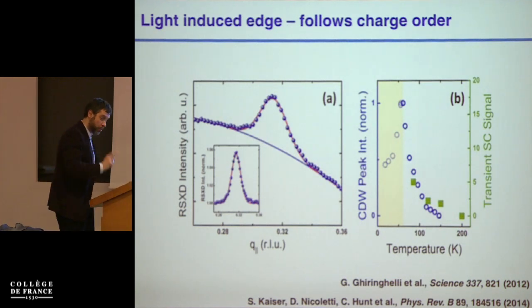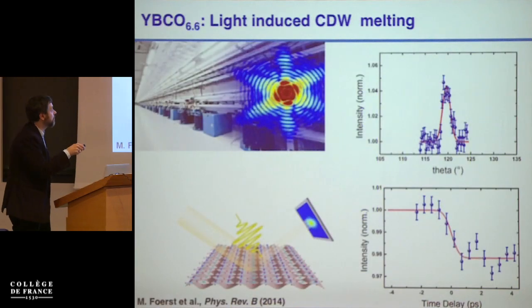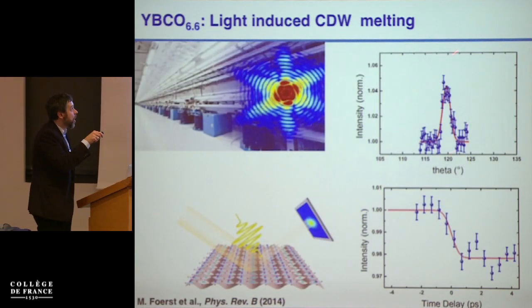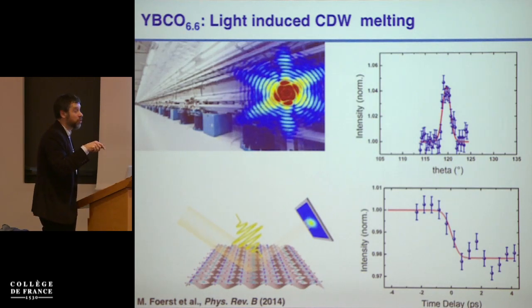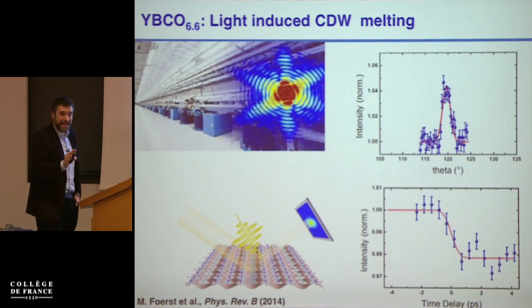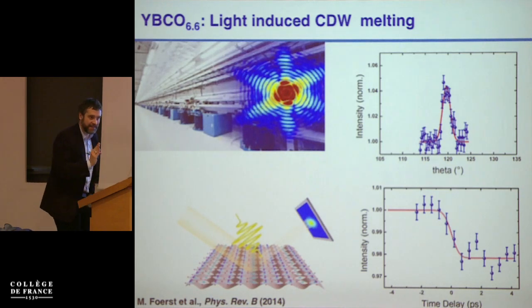And furthermore, if you do a pump probe experiment at the same laser on this peak that tells you about the charge ordering in 1/8 doped YBCO, you find that also this charge order goes away. So once again, at 1/8 doping, the observation in YBCO is the same as the one that you make in LSCO.